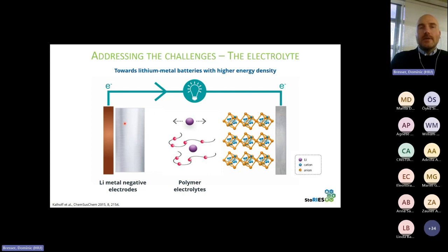So people thought, I think it's not yet 20 years ago, that potentially we could remove the lithium metal and then have a kind of lithium-ion battery, in the sense that the only lithium source is the positive electrode, but it's still a lithium metal battery because the lithium would be plated as lithium metal on the negative electrode, on the current collector, naked or modified. This is then frequently referred to as anode free, which is not fully correct, because there is no battery cell without anode and cathode, or a zero excess lithium metal battery.